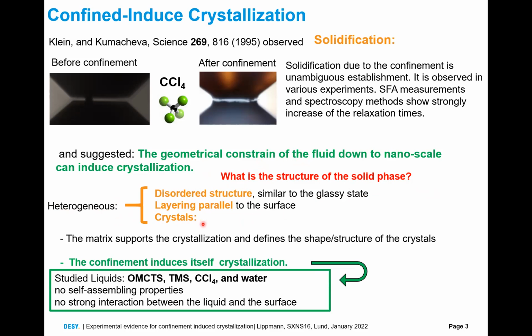Now we are talking about crystals in confinement. These crystals have two aspects. On the one side, the matrix can support the crystallization and give a shape to these crystals. It also can influence the crystal phase. But the question I would like to address in our experiments is really to prove whether the confinement itself, the constraint itself, can induce crystallization. For this, we use liquids with small molecules which don't have self-assembly properties, and interfaces which don't have a strong interaction with these liquids.